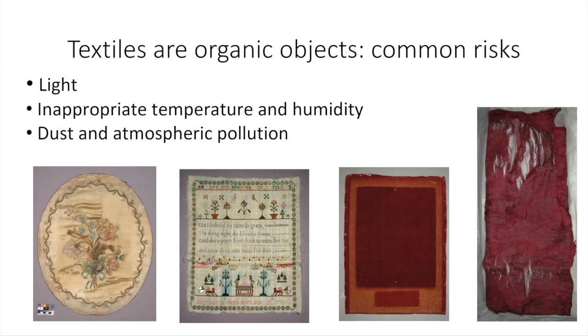Temperature, and in particular relative humidity, which is influenced by temperature, can also be very damaging. Too high a humidity can cause dye bleeding, as you see here, and it can cause mold growth and the corrosion of metal components, for example. Whereas too low a humidity can make a textile more brittle.